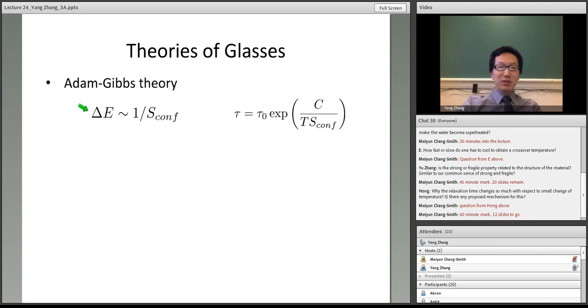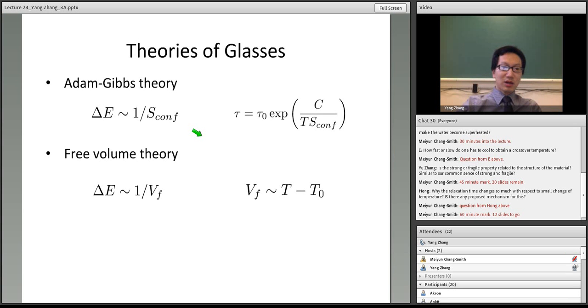So Adam-Gibbs theory works very well above the glass transition temperature and is widely used. The next theory that I want to talk about is the so-called free volume theory. Free volume theory was described a long time ago, and its opinion is almost the opposite of the Adam-Gibbs picture. In free volume theory, the activation energy is assumed to be inversely proportional to the so-called free volume.